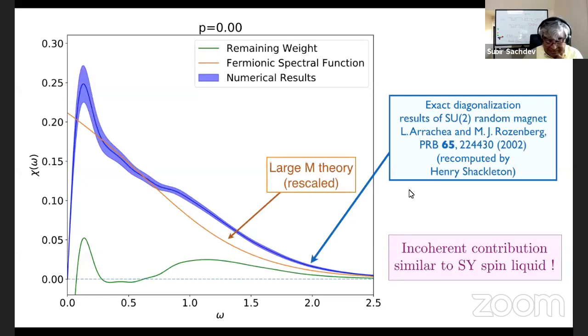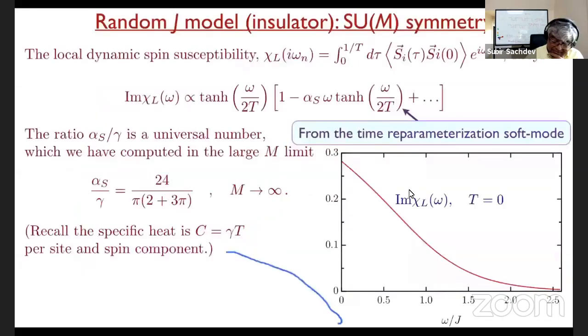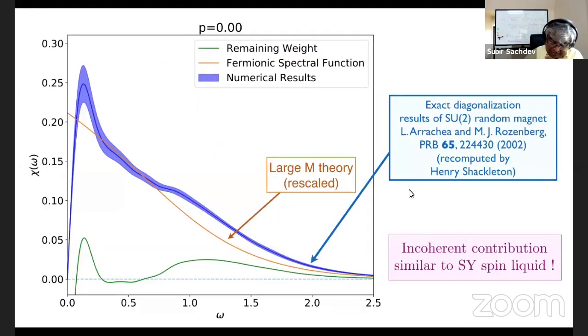So the first thing I would like you to notice is that this shape of chi of omega in this finite system is not too far from this function that you got in the large M limit. And in fact, here's the large M theory rescaled in some reasonable way to match this linear slope here. And it's not too bad. We don't quite understand the reason for this bump here. It may be because of some finite size effects and commensurability effect with finite systems. However, it's not too bad.